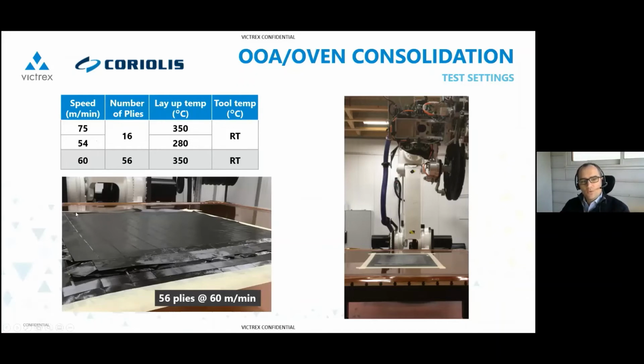So here, when you do out-of-autoclave, what you expect is just having a kind of tacking between each ply, each layer, because you will then consolidate it in the autoclave. So what is the minimum temp to achieve this stacking laminate, and at what speed? And we have been able to still achieve a pretty high speed for this temperature, at 54 meters per minute. So that's what we did, and we said, okay, let's make those panels and look at them.